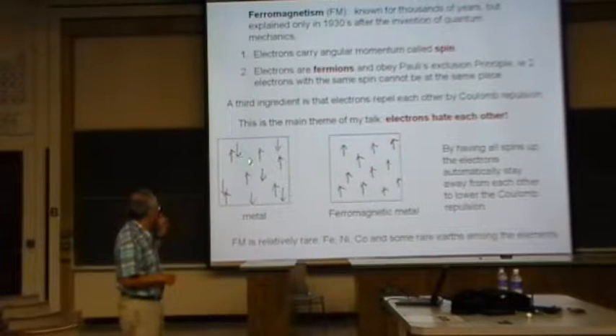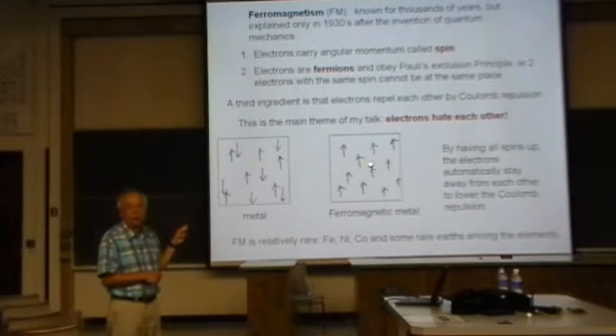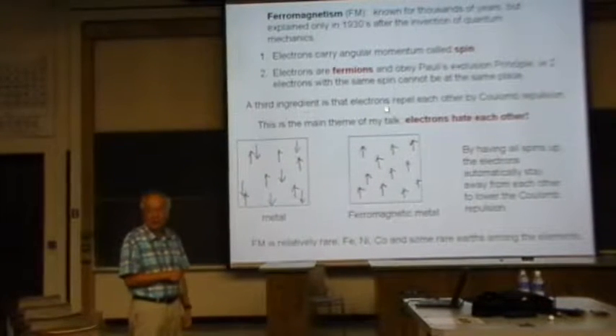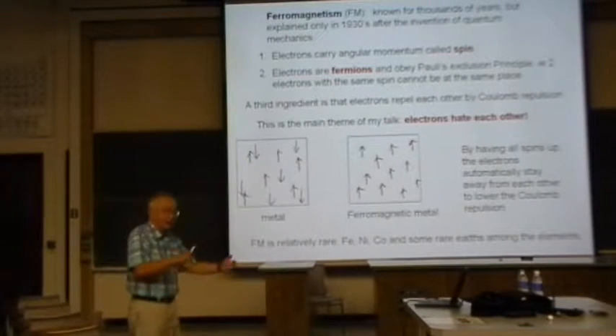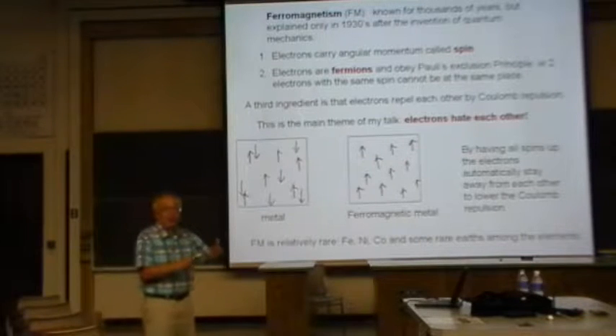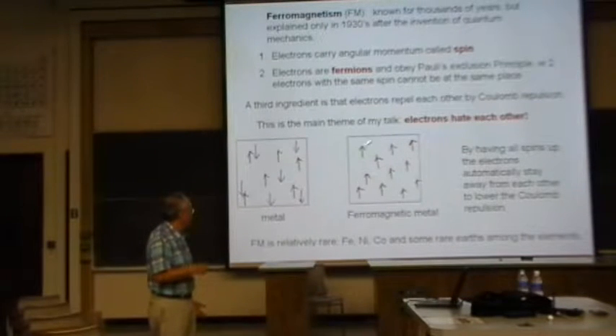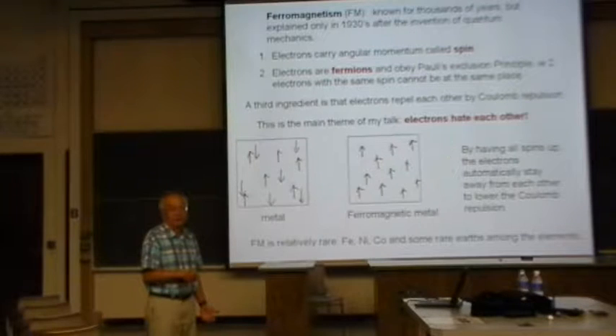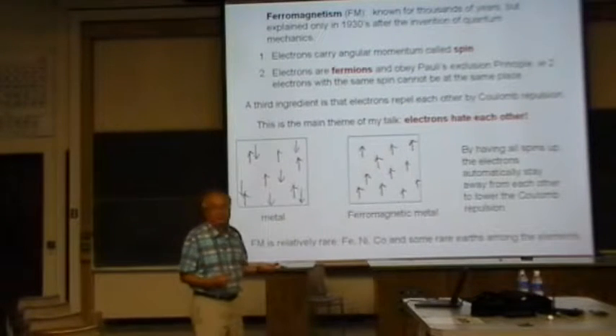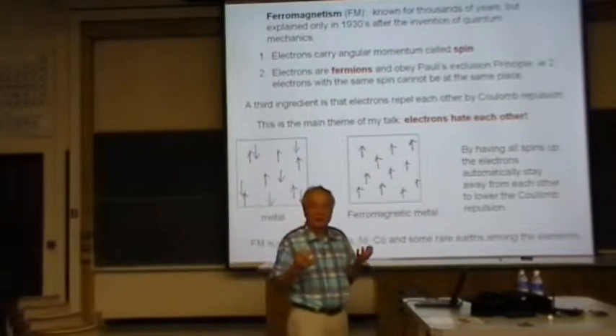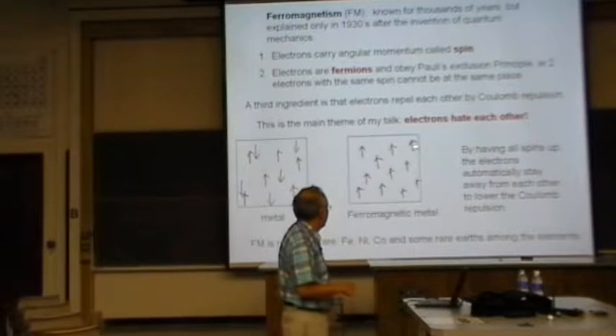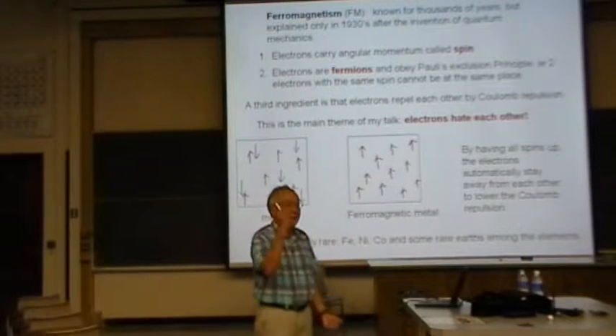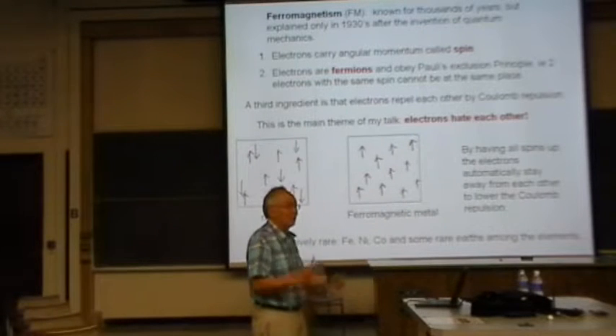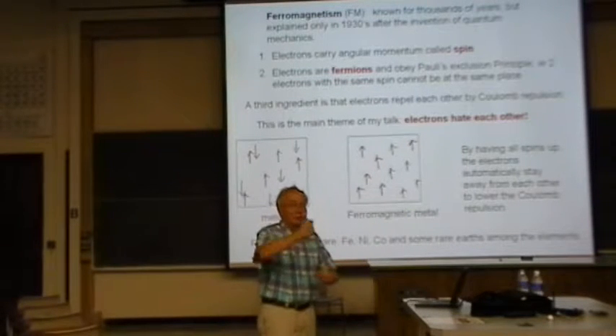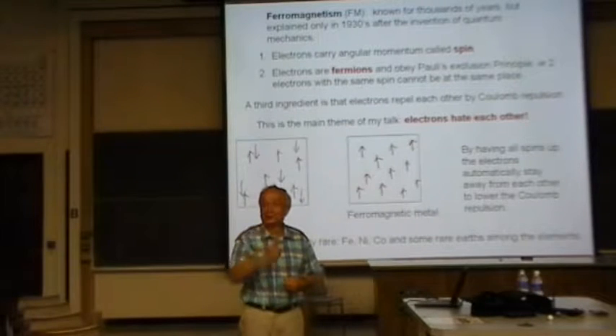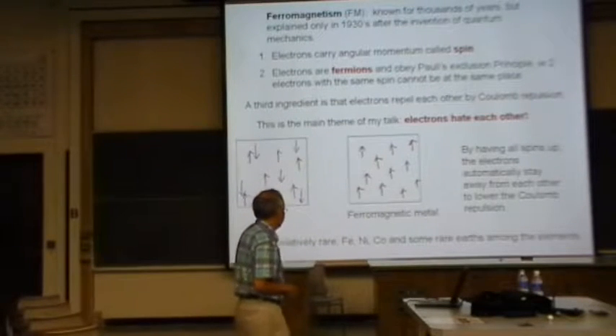But now look, this guy is much worse from the point of view of Coulomb repulsion. This guy costs me much more energy because these electrons are getting close to each other and it becomes very costly. Right? So I can lower my energy by going to this state. Okay? And this is the origin of ferromagnetism. The system decided it can lower its energy by having all the spins aligned. Right? When all the spins align, because the spin carries angular momentum, the entire sample is carrying angular momentum, and that creates a magnetization, which gives you a ferromagnet.